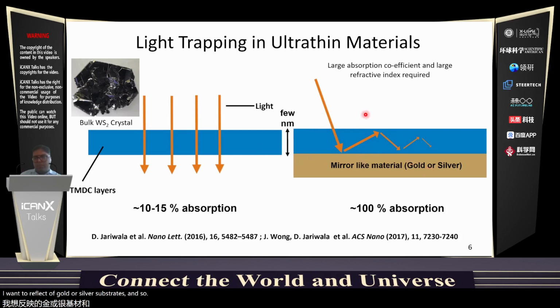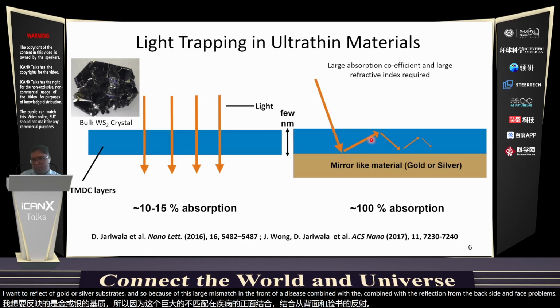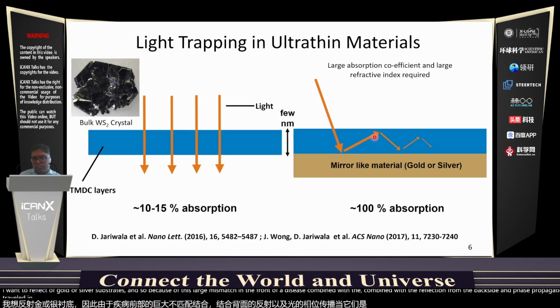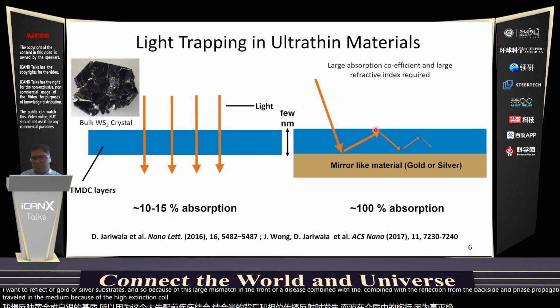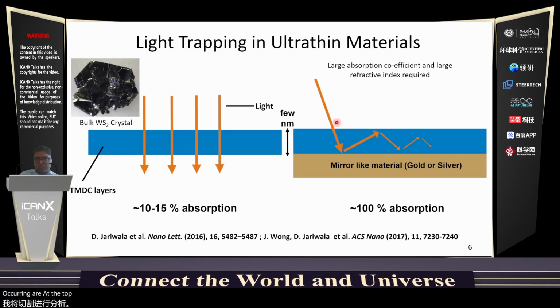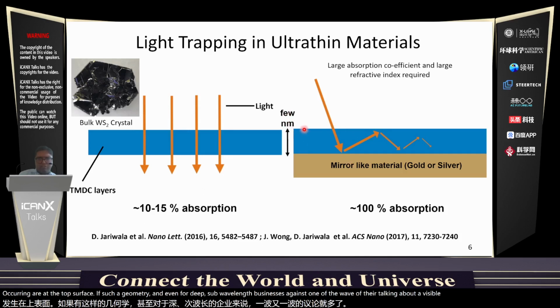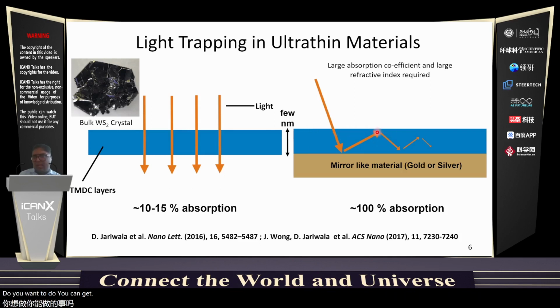And so because of this large mismatch in refractive indices, combined with the reflection from the backside and phase propagation of the light that happens while the wave travels in the medium, because of the high extinction coefficient, you can have destructive interference occurring at the top surfaces in such a geometry, even for deep sub-wavelength thicknesses. Okay, so now the wavelengths we're talking about are visible frequencies, but the thicknesses we are talking about are just a couple tens of nanometers. So even in deep sub-wavelength thicknesses, you can get nearly perfect absorption.